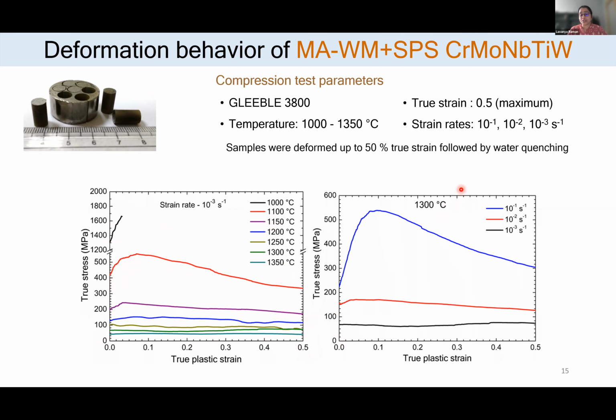So at higher temperatures, when we deform at different strain rates, that is, when you deform it in a very slow manner or very fast, the alloy behaves in a different way. At higher strain rates, it shows a peak hardening followed by softening. Which means that initially, up to a certain strain, the alloy work hardened, so we have to apply more and more force to deform the alloy. Whereas once you cross a certain barrier, it is easy to deform the alloy. When we do it at a very slow strain rate, the material has enough time to rearrange the dislocations inside it, and it exhibits a steady state behavior.